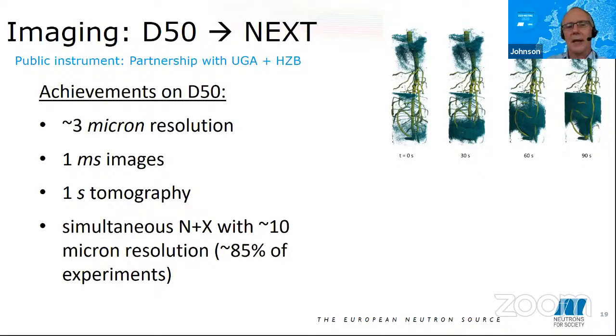And as I say, X-ray capability is there, and actually almost all experiments use a combination of neutron and X-ray imaging. And the sort of thing they can look at is illustrated on the top right. It's the take-up of water by plant roots. And you can use HD substitution here very nicely, because you can essentially let D2O flow into H2O, so you can see how this water uptake takes place.